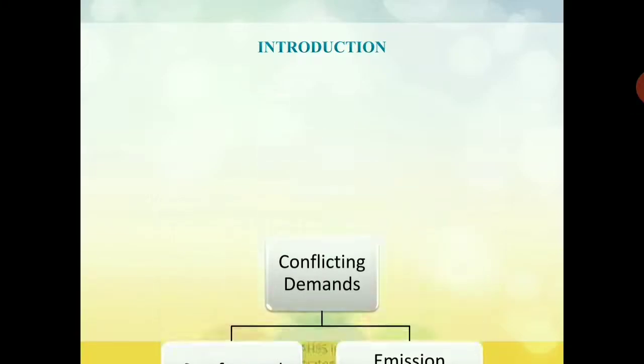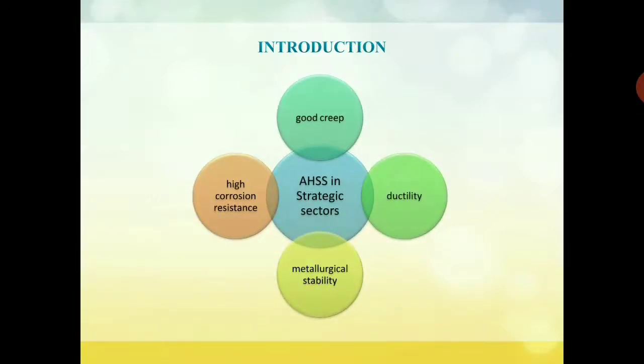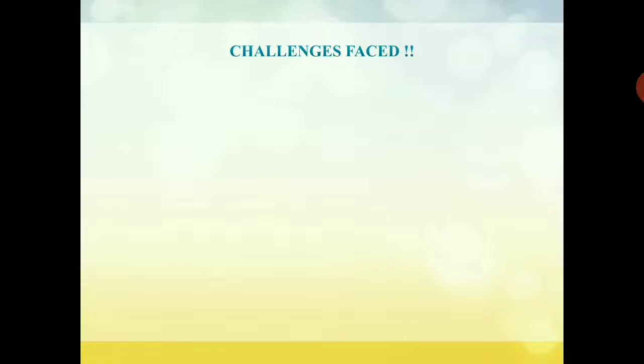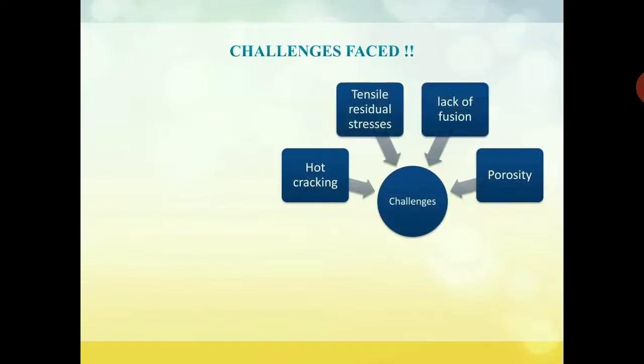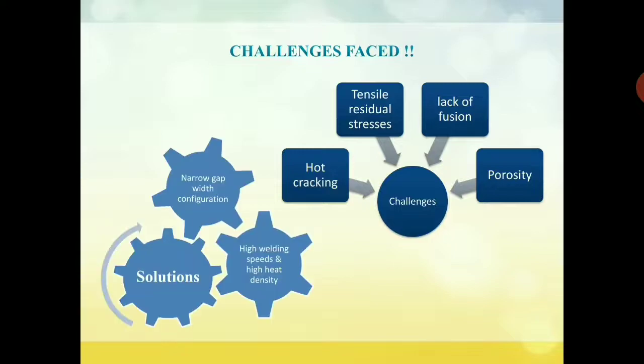Advanced high-strength steels have come to the rescue due to their metallurgical stability, high corrosion resistance, good creep, and ductility properties at elevated temperatures. Typical challenges that are faced during the welding of AHSS steels are the induced tensile residual stresses caused by the high coefficient of thermal expansion of steels, the lack of fusion between welding tracks and groove side walls, hot cracking, porosity, resulting in the degradation of mechanical properties, and reduced corrosion resistance of the welded components.